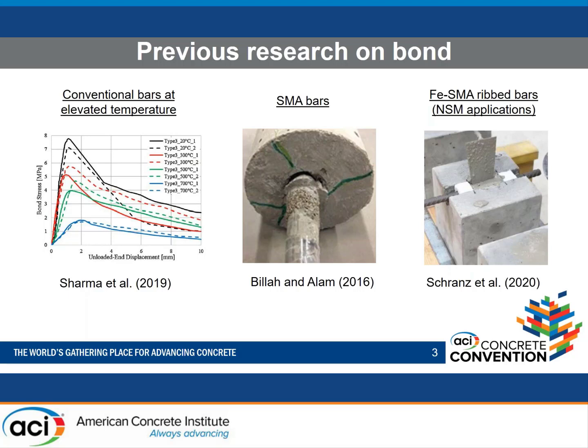And of course, as we all know, bond has been extensively studied for conventional steel rebars, but still this material is a different material for different reasons. First of all, it has different mechanical properties, and also due to the activation temperature that we need to apply in order to activate the shape memory effect, there might be a possible deterioration of the material while activating the bars. And this was already shown today by Professor Sharma, who presented the first presentation, and he showed us that even for conventional steel rebars, there is a bond reduction as the temperature increases.